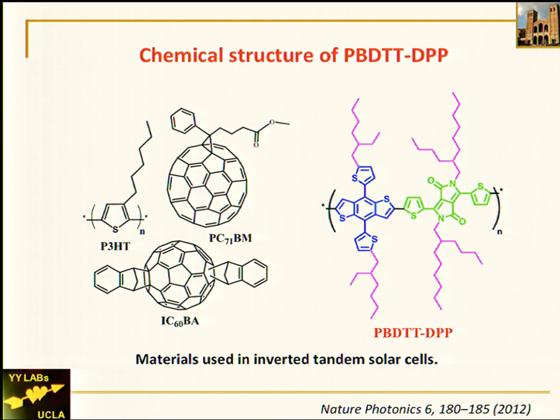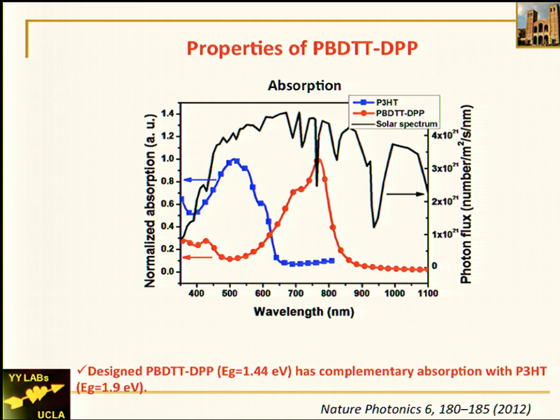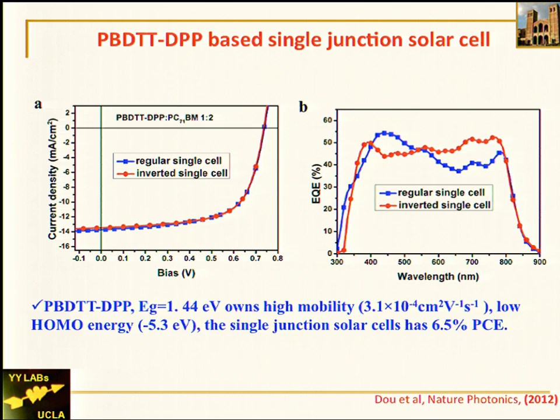My student Letian Dou, during his preliminary PhD exam two years ago, decided to make a material that only absorbs in the infrared. This is the polymer PBDTT-DPP. The acceptor ICBA is a molecule synthesized by Professor Yongfang Li's group in China at the Institute of Chemistry. PCBM and P3HT are commercially available. You can see the absorption curves are much more separated. We have P3HT with ICBA and the infrared polymer, giving complementary absorption all the way up to about 800 nanometers.